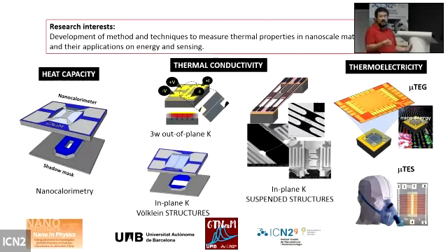Heat capacity nanocalorimetry: we have developed systems able to measure heat capacity on samples below nanograms, in scan areas of millimeters. It essentially means that we are able to measure ultra-thin films below the nanometer of effective thickness. We have also developed different techniques to measure nanoscale materials, either on nanowires with suspended structures, or ultra-thin films with suspended structures.